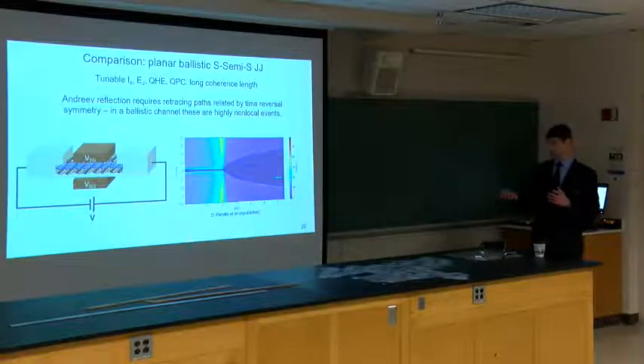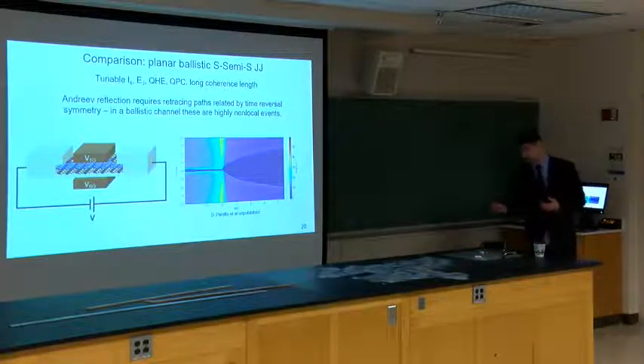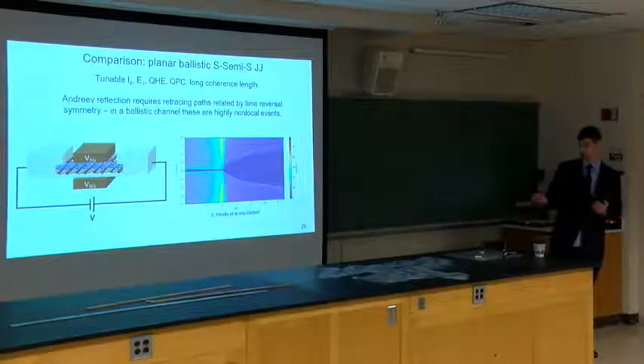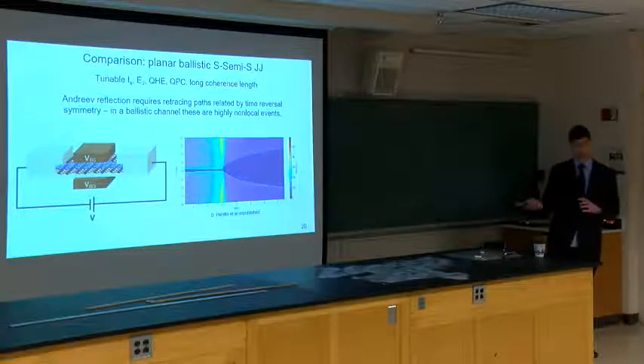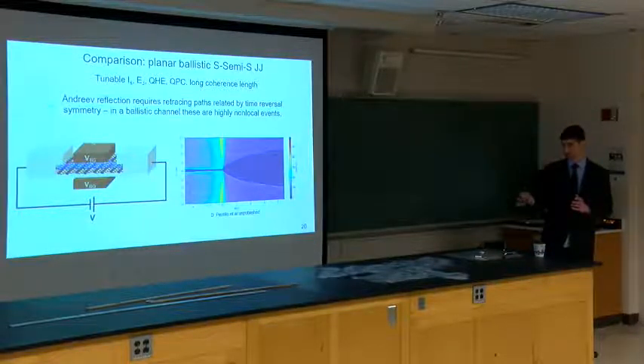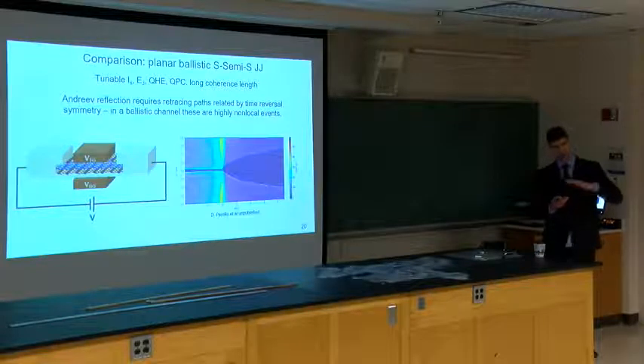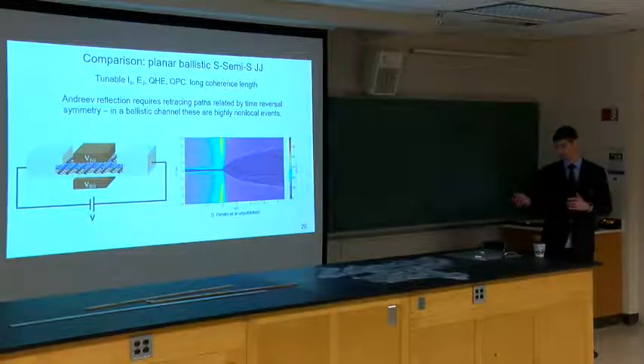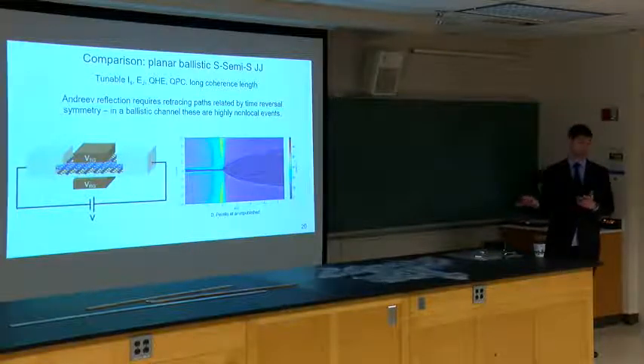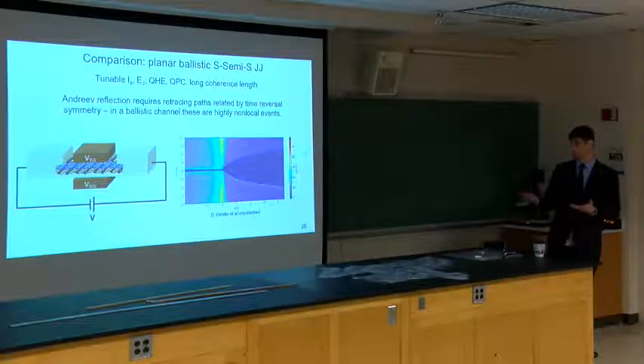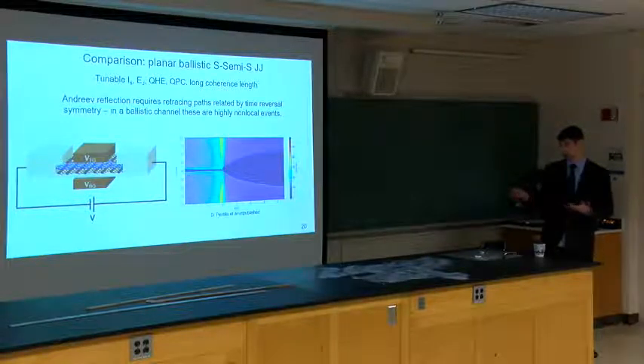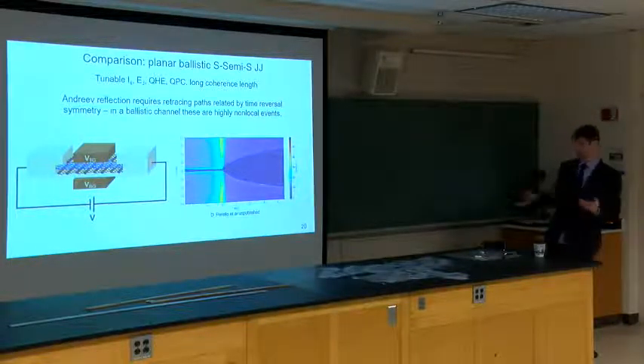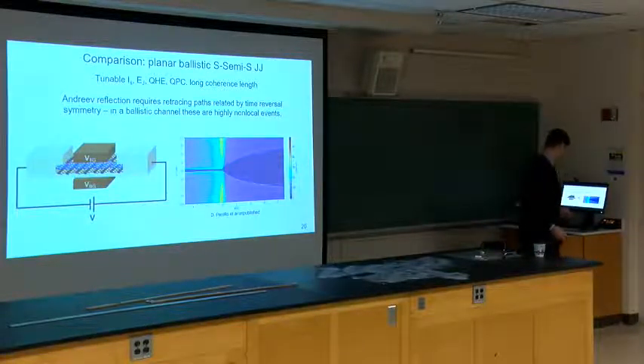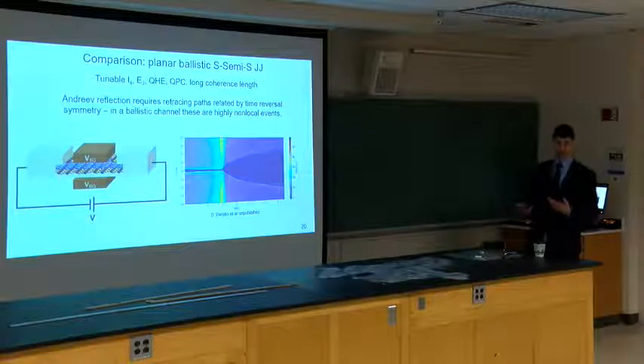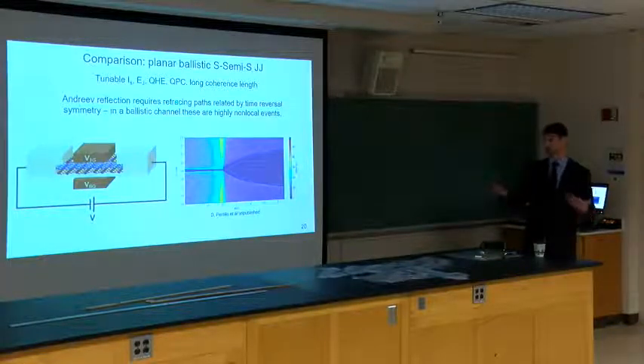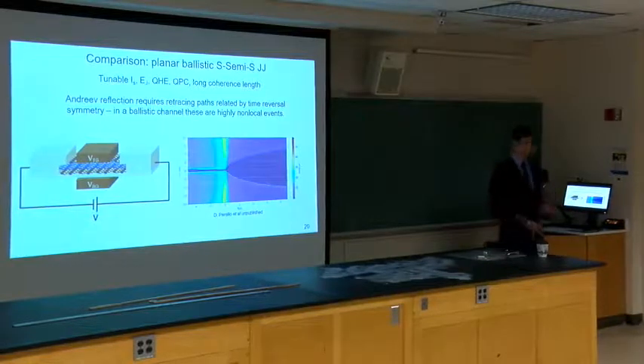So one of the things we can do is, this is one of my unpublished data sets. So the x-axis here is the gate voltage. So the gate is the electric field across here. So instead of like in the previous system where we had a superconductor, a normal, and a superconductor on the bottom, here the superconductors are on the sides and the channel is actually a semiconductor. Well, if we change the gate voltages, we can modulate the critical current by an order of magnitude or even more. And also the contacts can be extremely long. And we can look for other physics that are not just associated with superconductivity, such as the quantum Hall effect, make quantum point contacts, and we have a very, very long coherence length.